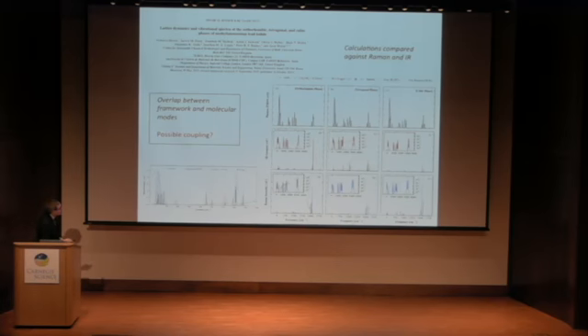And that can be seen in these graphs here, first of all from their calculations. Here they plot phonon density of states in all three phases, so the orthorhombic, the tetragonal, and the cubic. And the purple spike here is that associated with the framework, the lead iodide framework. And these little green spikes are associated with the molecule. You can see there's a big overlap at fairly low frequencies here, or low energies.